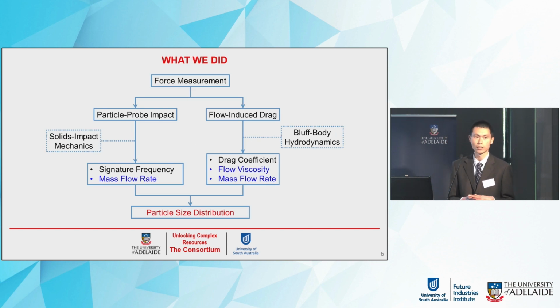To lower the cost of the sensor, we have developed a unique way based on force measurement. The probe is subject to vibration under particle impact and also flow-induced drag. Depending on the vibration frequency range, we apply two different mathematical models to extract useful information from the signals. That includes the mass flow rate and also the flow viscosity. That's why this is a multifunctional sensing system. With all the available information fused together, we will be able to obtain the particle size distribution.